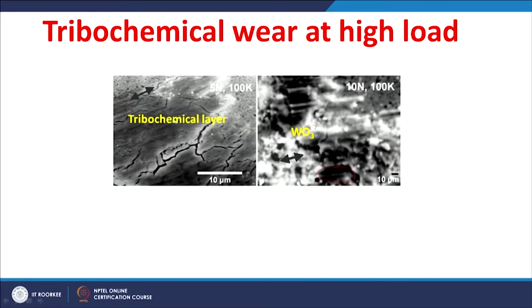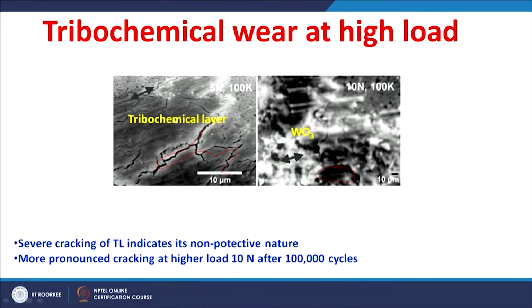than the grey region. So, it is believed that this grey region has iron and iron oxide, while the white region, the bright contrast, shows a tungsten oxide rich layer. So, we will also confirm this with EDS and other analysis. Now, these surfaces also indicate the tribo layer is severely cracked. The severe cracking of this tribo layer indicates it is non-protective in nature.